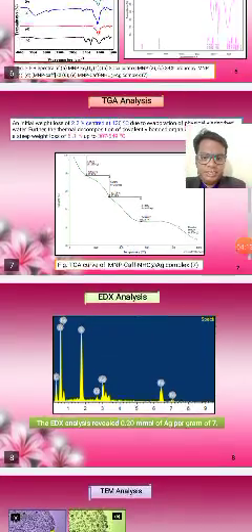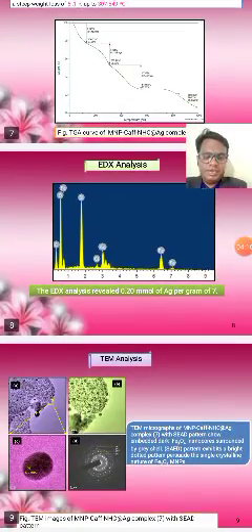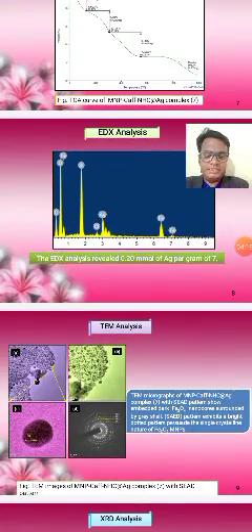We evaluated the final product, the N-heterocyclic silver complex anchored on magnetic nanoparticles, to check its thermal stability, and it was found thermally stable in thermogravimetric analysis. These are the weight losses. The initial weight loss is due to physically adsorbed water, then the loss of organic moieties. We further checked its chemical composition using energy dispersive X-ray analysis. This is the EDAX spectra, which shows the main elements are iron and oxygen, which is attributed to the Fe3O4